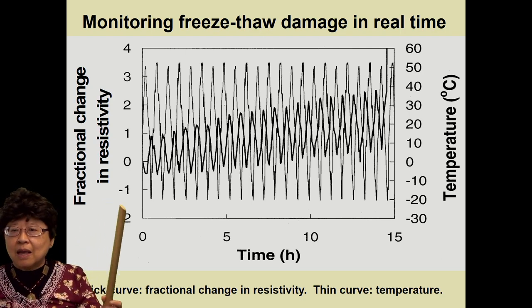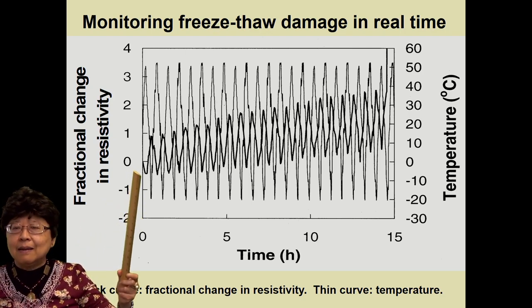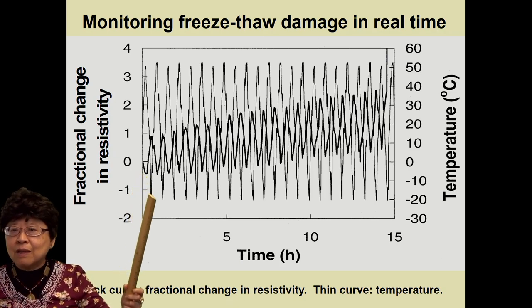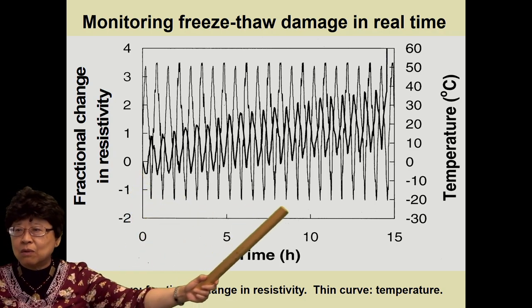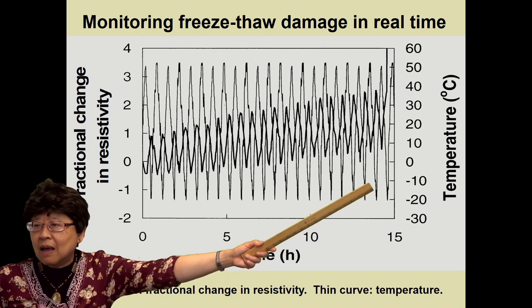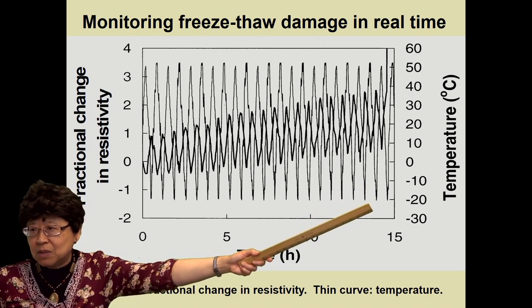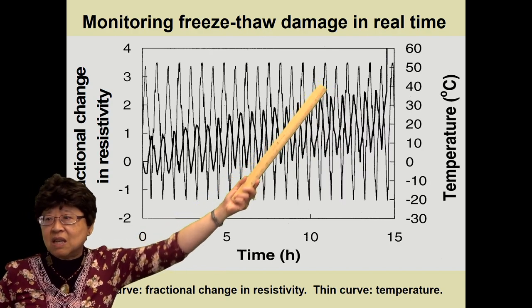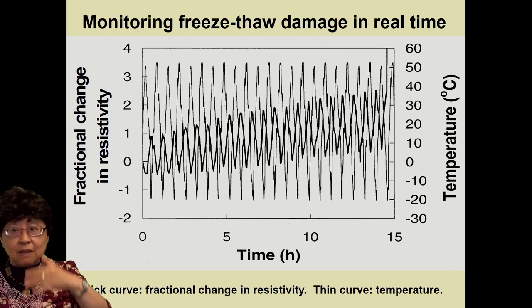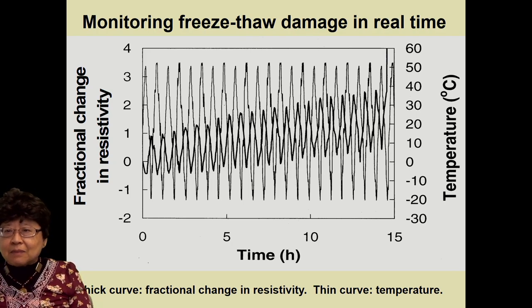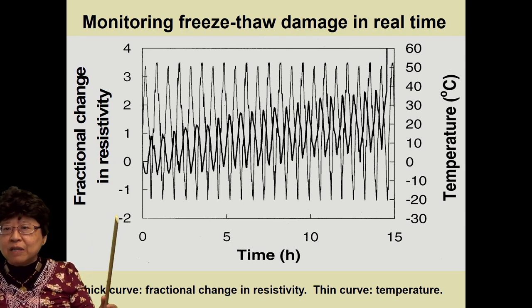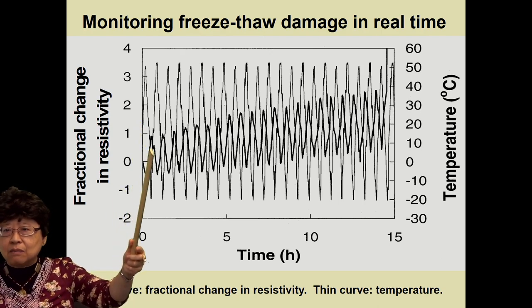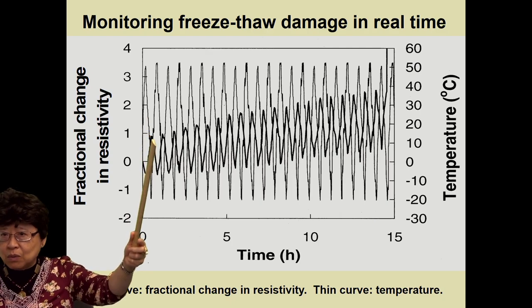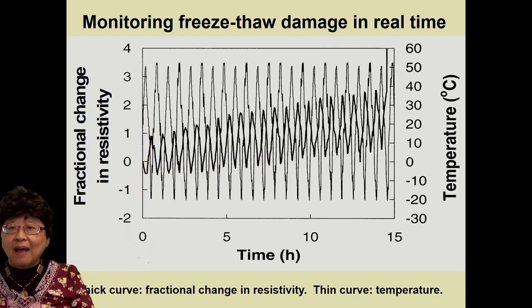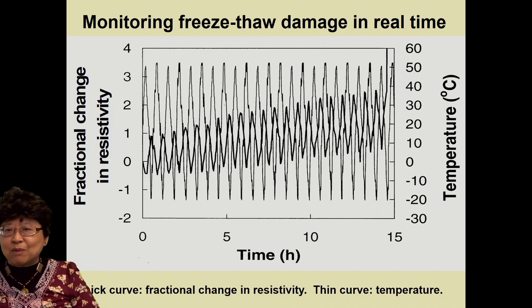And this shows in bold line the resistance and in thin line the temperature. And you note that the temperature cycles between minus 20 degrees C, which is below zero, and plus 50 degrees C, which is above zero. So it's freezing, thawing. Every time one cools, the resistance goes up. And that's another story. I won't go into that.